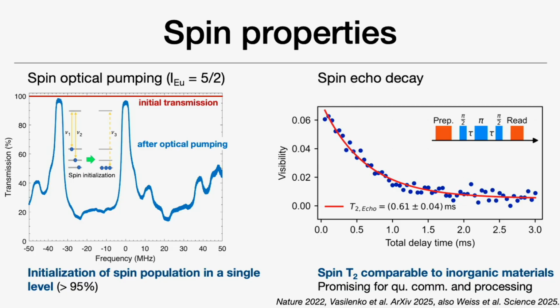We also looked at the spin properties. We could also do this spin optical pumping. Basically, we start from an initial absorption. Here we have a very small scale in frequency or wavelength, if you like, so on this scale, the initial transmission is completely flat. If we shine lasers at 2 different frequencies, we start to have this very complicated spectrum. This is due to the fact that europium has a nuclear spin, and by this optical pumping technique, we can also polarize these